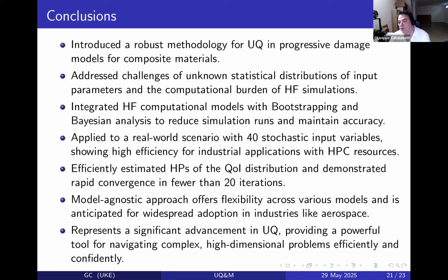We have had the experience of this. There are some material parameters for which it has been very complicated to measure the property. For example, interlaminar fracture toughness: DCB is now a standard, and has been for 20 years, but other tests like MMB or ENF have been certified or made part of the ASTM norm only in the last few years. And there are other very important properties that we use. There is, for example, the intralaminar fracture toughness.